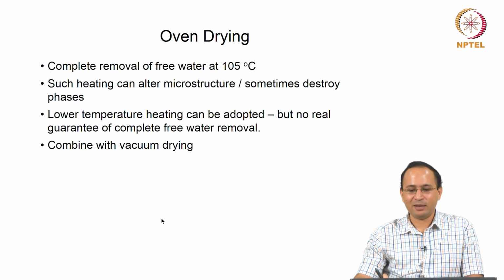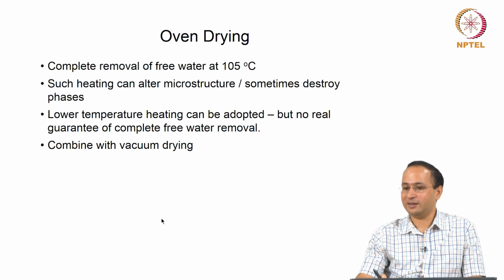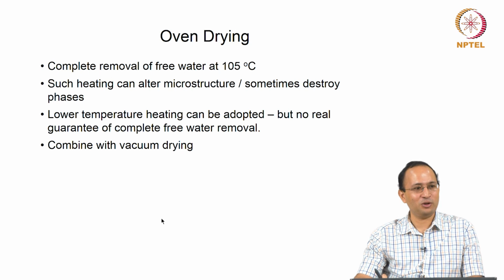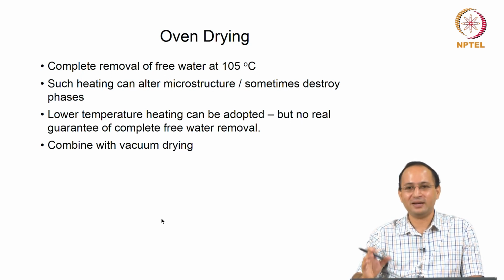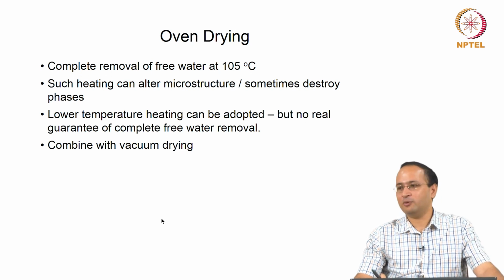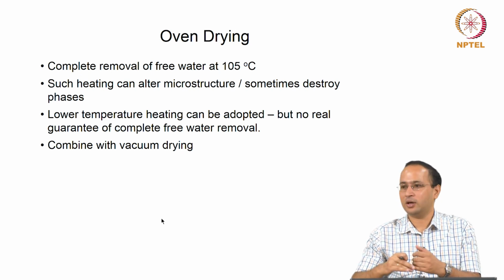Lower temperature heating can be adopted, you can do that, but then you are not sure whether you will remove the complete free water or not, that is the challenge. You can use 50 degrees C, 40 degrees C, but then it will take forever and you are not sure when you are going to remove it completely. Usually it is combined with vacuum drying. Make sure that your sample is in vacuum.